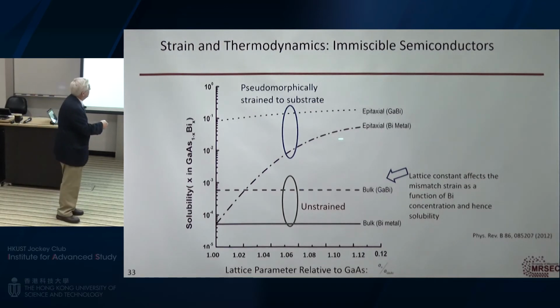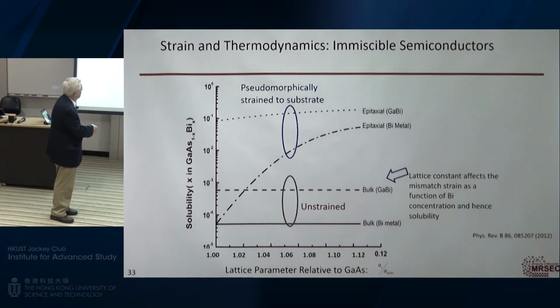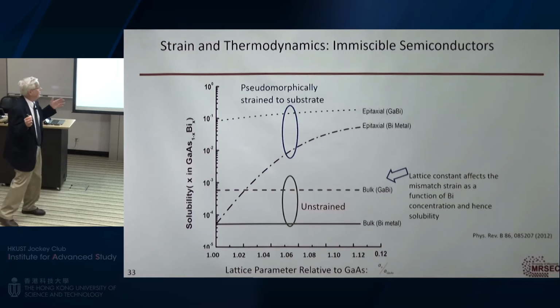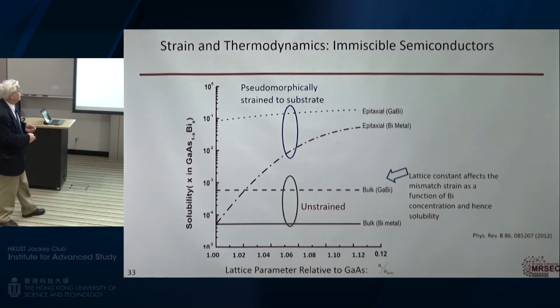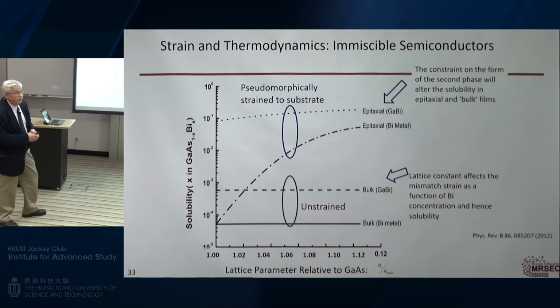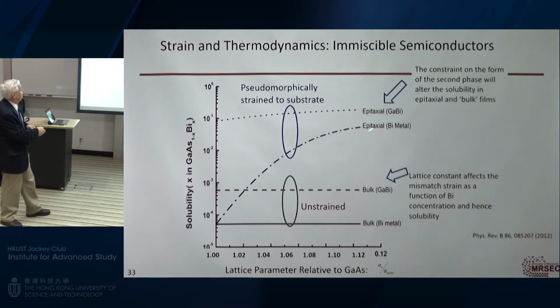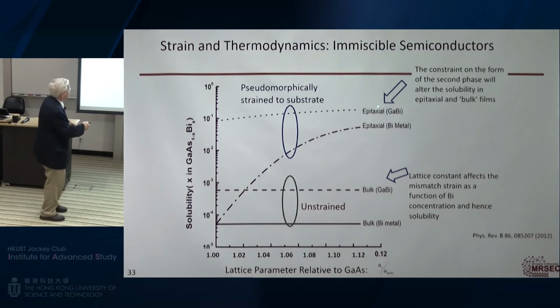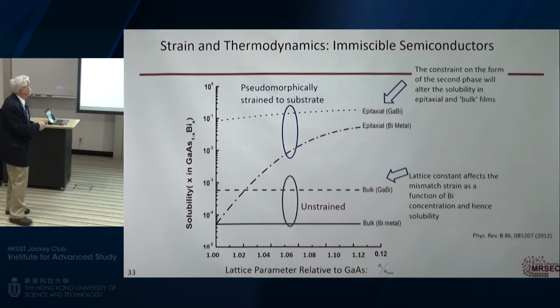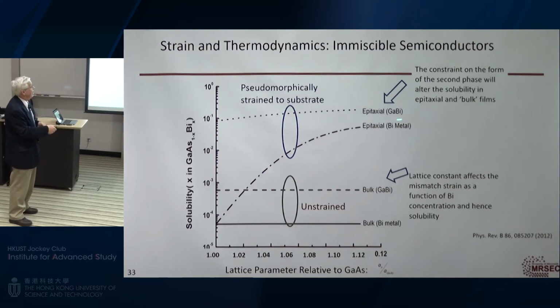If I actually make it an epitaxial system and it becomes strained to the substrate, meaning that the crystal doesn't have exactly the same lattice parameter, I actually can incorporate more bismuth into it. And actually, if I force it to decompose by forming gallium bismuth instead of bismuth metal, I actually get a fairly high solubility. And the reason for this is that strain is a thermodynamic energy term, and it's stabilizing this structure because it does not want to form this coherently strained material.